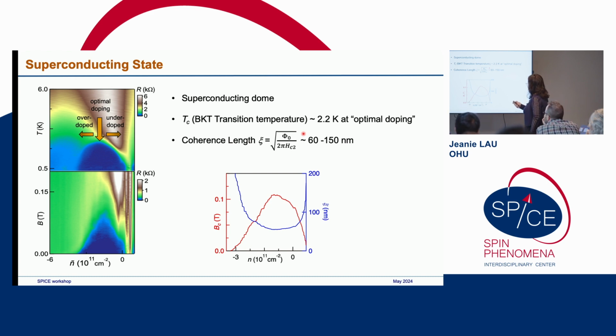So for example, here we're looking at the resistance as a function of charge density, which is the horizontal axis. The upper graph plots density and temperature, and the lower graph plots the magnetic field. And the dark blue area is the superconducting region. So we can see that now this disappears.